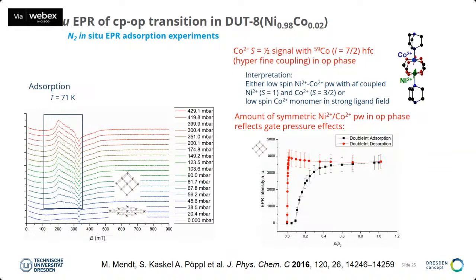So you can see this here, many, many lines, basically. What you can do now is, together with the group in Leipzig, Andreas Pöppl, we developed a setup where you can dose gas to the MOF and then monitor the EPR spectra, and you see that this symmetrical spin structure, the signal with the multiplet structure, comes up at a very defined pressure, here at about 40 millibar, and then this is only for the adsorption branch, stays constant. You can integrate this signal and then follow the adsorption branch and also the desorption branch, and in this way you get some microscopic insights into the structural transformation.